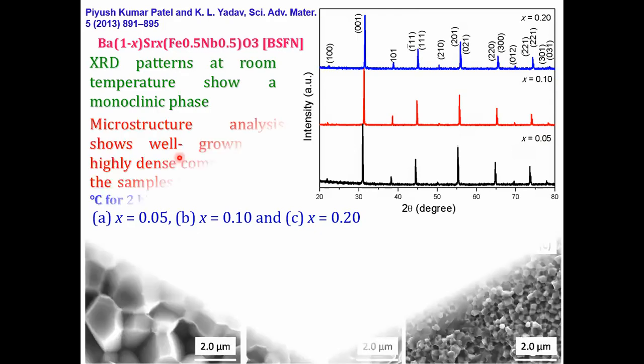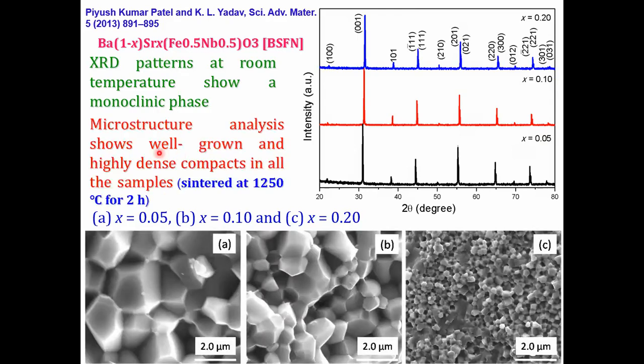The XRD patterns show the same structure, monoclinic phase. But when you see the microstructure analysis, it shows well grown grains - this is for 0.05, this for 0.1, and this for 0.2. When doping, replacing barium with strontium, the grain size is much better at 0.05, and after that it is decreasing. When grain size decreases, grain boundaries increase, and grain boundaries have less energy and lower dielectric constant with respect to the grains themselves.